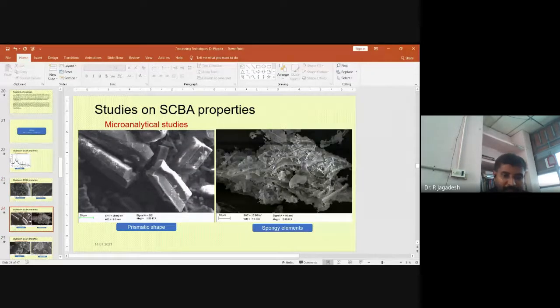If you see the prismatic shape of the sugarcane bagasse ash, it is crystalline in nature. As observed in XRD, it is confirmed with the help of SEM, the scanning electron microscope. You can observe the particles are crystal-like, prismatic in shape. This indicates that the particle is not reactive in nature. Another indication that the material is not reactive is the spongy type, which indicates a large amount of carbon content, as observed with the help of EDX, energy dispersive spectroscopy analysis.